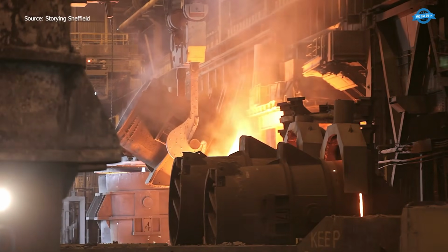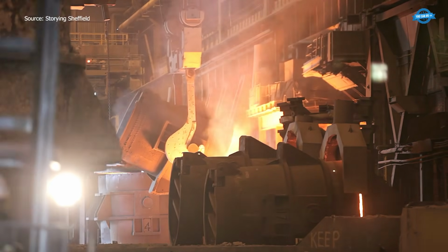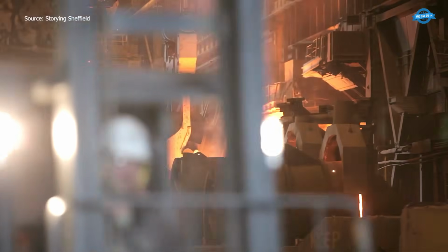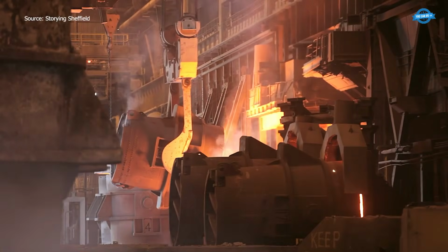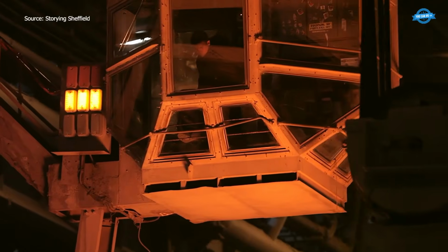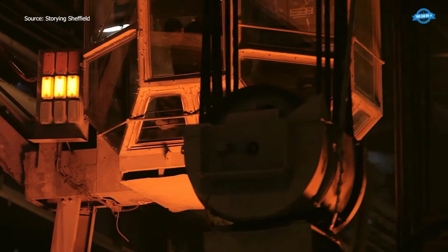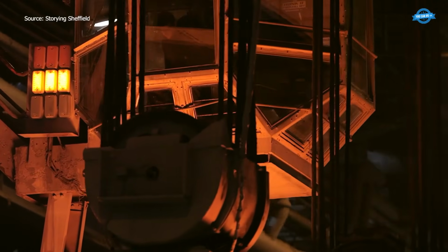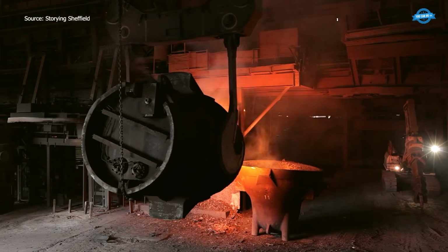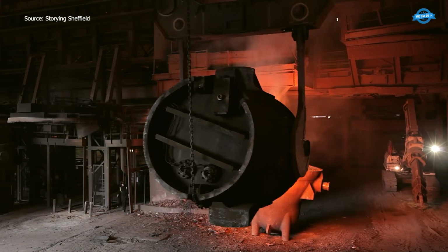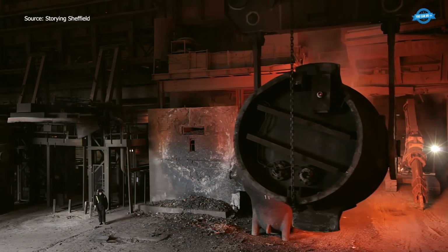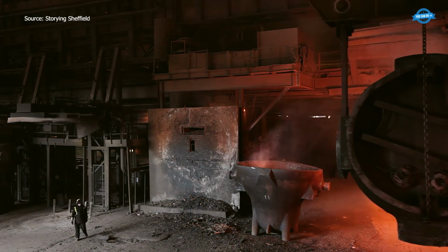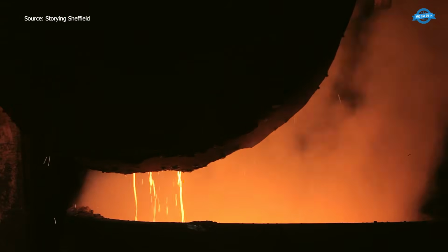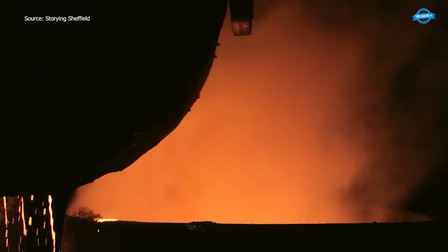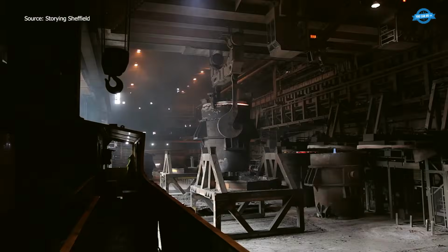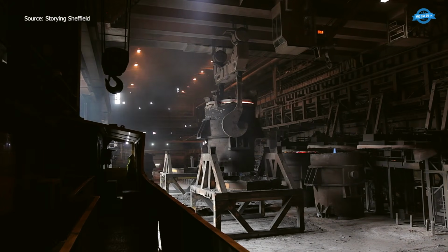Once the bath stabilizes, refining takes over. Slag is managed to pull out unwanted elements while alloying materials are introduced to shape strength and performance. These additions are timed to work with the melt, not fight against it. Ladles receive the steel and carry it forward, still glowing, still active. That heat isn't wasted time, it's a narrow window that has to be used right. At the ladle furnace, composition and temperature are corrected again, not rushed, not guessed. Each tweak has a reason, even if it looks subtle from the outside.